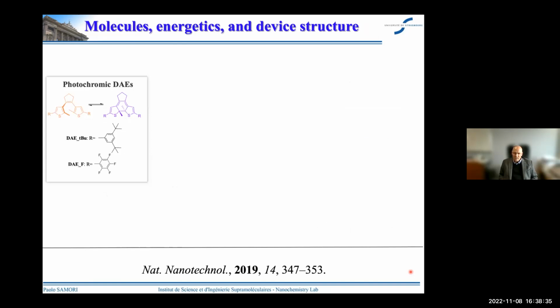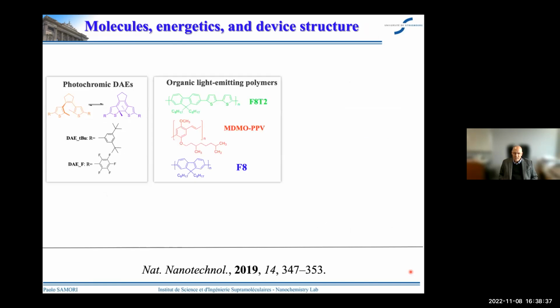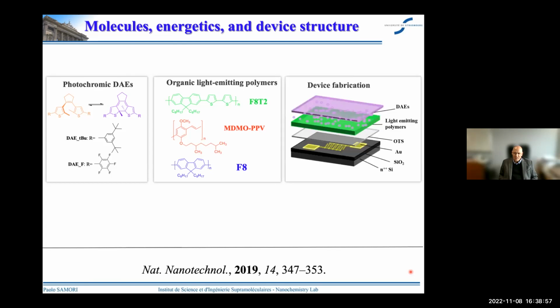We first of all have defined the light emitting polymers we wanted to play with. These are commercially available, and have already been proven to be the right choice if you want to make a light emitting transistor. And so we have one that emits in the green, one in the red, and one in the blue. Based on their energy level, we have selected a different type of diarylethene. And I use again the permeation of this diarylethene through the layer of the semiconductor in such a way to have this kind of blending taking place.